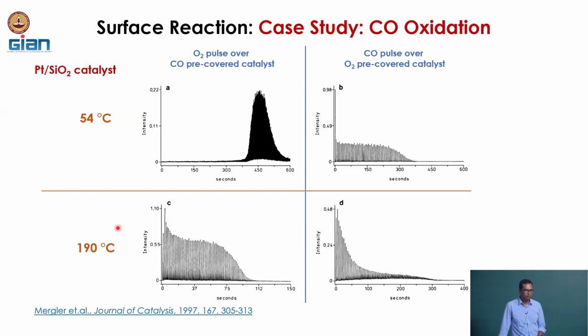So, when you are at high temperature, although you have pre-covered the surface with CO, because of the high vacuum condition of the TAP and the high temperature as compared to 54 degrees Celsius, some of those COs are loosely bound, not as strongly bound as in the case of 54 degrees Celsius. And because of that, you now have more available sites for oxygen adsorption, and hence your reaction just goes on. Okay? But our target is that we want the catalyst that is active at low temperature.